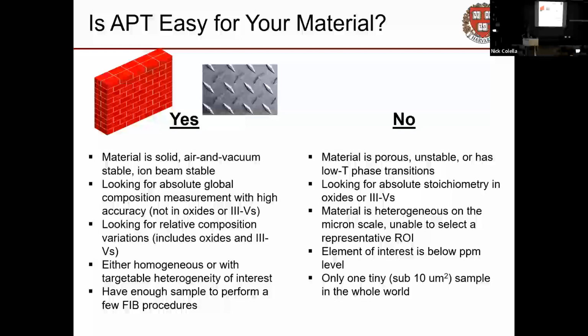Highly heterogeneous materials. Materials for which what you care about is seeing atoms that are present at levels of less than a part per million. Why is that a problem? Because we do see more or less all the atoms. That's a problem because of time. To collect 1 million atoms, which is a small data set, takes you about 20 minutes. If you want to get good statistics on something that's present at 1 part per million, you need to collect 10 or 100 million atoms, which means you're looking at a many-hour run.